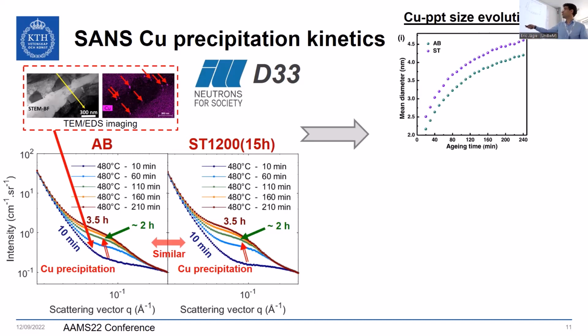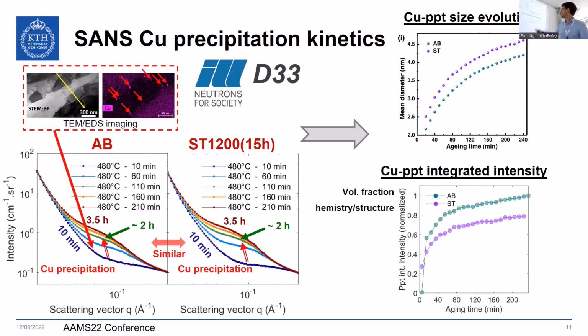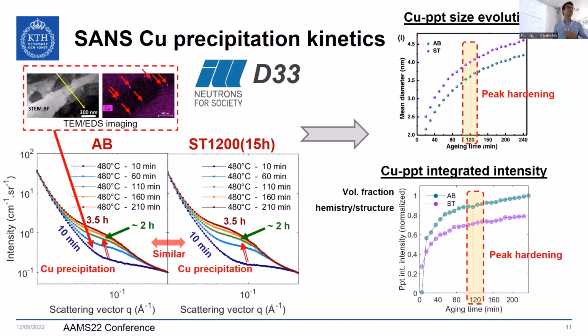Here, from this curve, you can do model fitting and then extract the mean diameter of precipitates for the as-built and solution treatment. You see how it has evolved, and you can also extract the integrated intensity, which is directly related to the volume fraction of your precipitates. And you see that it's increasing and reaches a kind of plateau. After 2 hours, we basically have nucleation and growth of most of the copper precipitates, which explains why we have this peak hardening at 2 hours. And then after that, we have certainly coarsening of the copper precipitates.